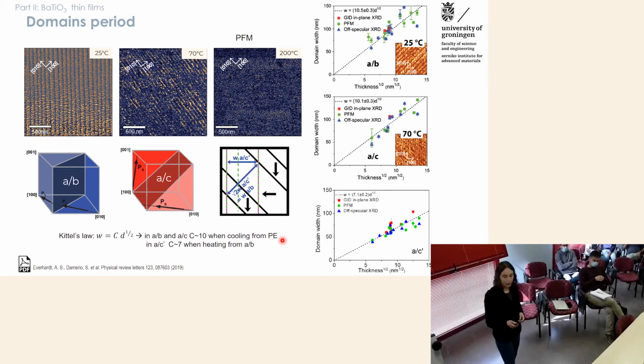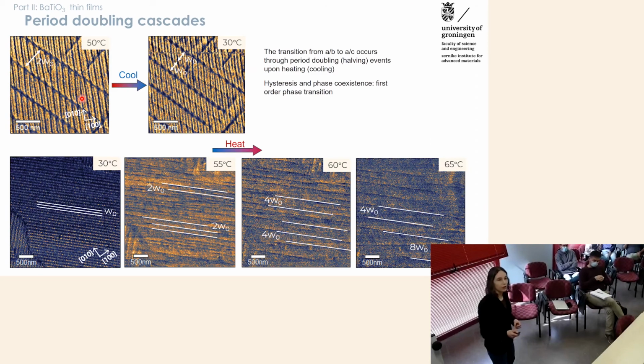And what we can do is also measure the phase transition, following it through the cooling process in the PFM, because this is quite a slow phase transition. And what we observe is, for example, when you cool down from the high temperature phase, we start having domains of the low temperature phase with a certain periodicity, and the new domain walls will nucleate exactly in the middle of the pre-existing domains. And the phase transition will occur through these sequential periodicity doubling events. And the same happens when we measure upon heating up. So we start with a certain periodicity, and then the domains disappear upon period doubling cascades.